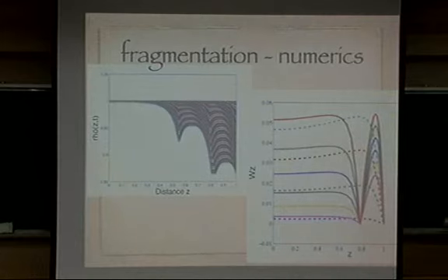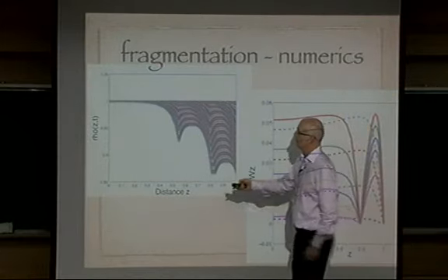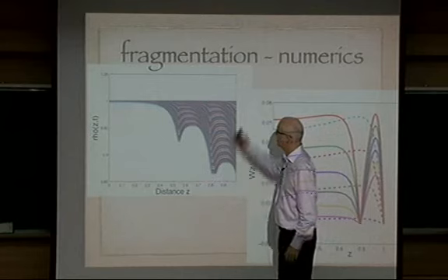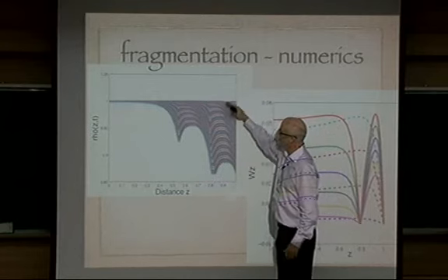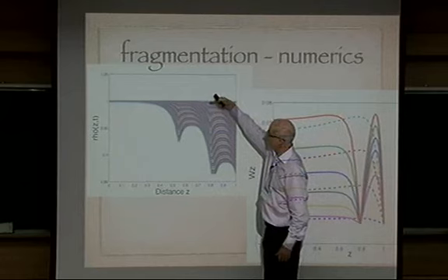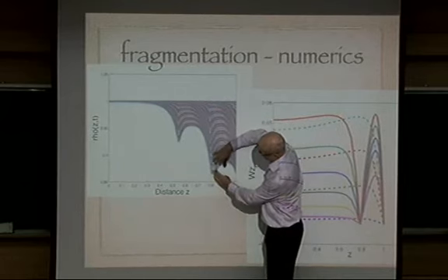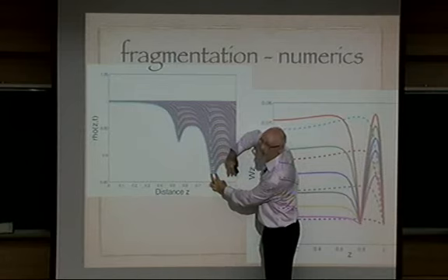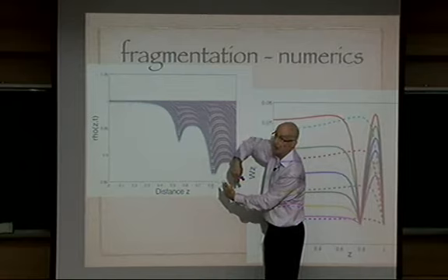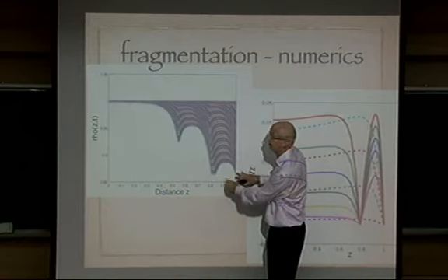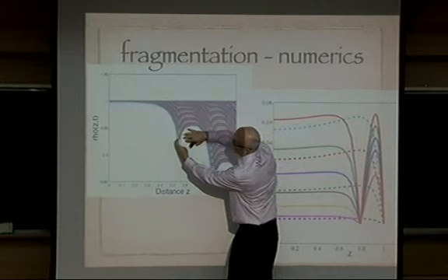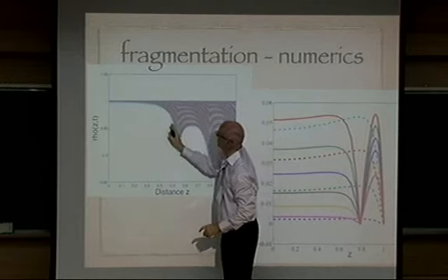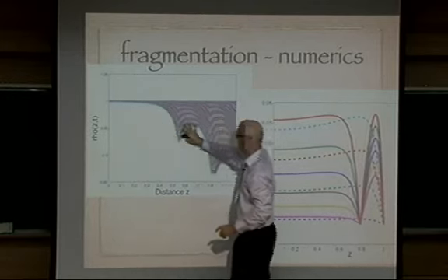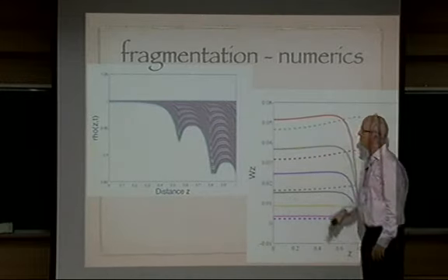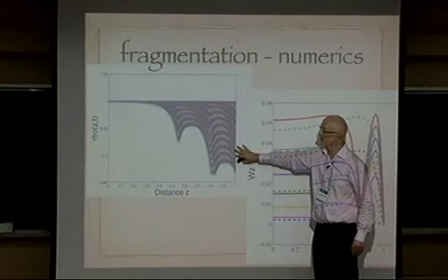So the result of that is to give me pictures like this, so I can give you pressure or density versus distance at early time and then late time, so the pressure dropping, and then a bit breaking here, so the pressure there drops faster. And you see as this bit moves away, there's a constant pressure region in the gap between. There's still constant pressure in the gap between. So I'm not solving the flow of the gas at all in gaps, just the flow in the rock. And here's another bit broken off here, and it's moving away too. And this bit's glued in, and eventually a bit will break in here as well. So you see that. That's the pressure or the density, they're related, dropping.